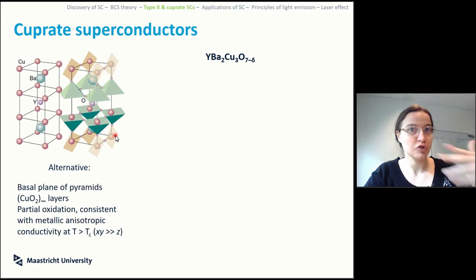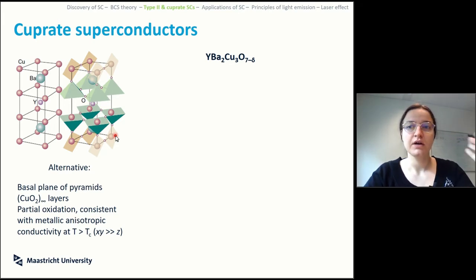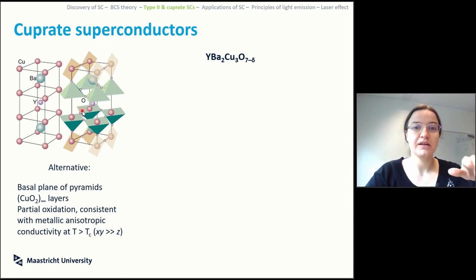So when the material is not superconductive at room temperature, if you make a crystal of yttrium barium copper oxide, you have delocalized electrons in the XY plane. This means that if you connect your measurement of conductivity on the crystal anisotropically, so if you connect it on the Z direction or the C direction, you don't see a big conductivity, but the conductivity is much higher in the XY plane than it is when you go over there. So it's a 2D layered conductivity, even though the structure is 3D.